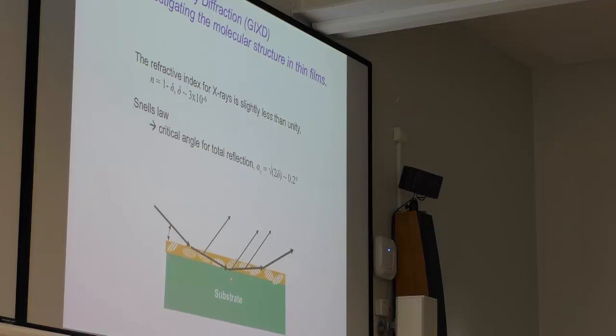Right? So this means that even though we are working with hard X-rays that are famous for being extremely penetrating, the X-ray in this case will not go into the substrate, it will be reflected off. And because of this, it will be extremely sensitive to whatever material you have on the substrate, right? So in this case, it is a thin film, and you can see we get essentially no background scattering from the substrate, but we get scattering from inhomogeneities in this thin film, which happens to be deposited on the substrate. Was that clear? Yeah?